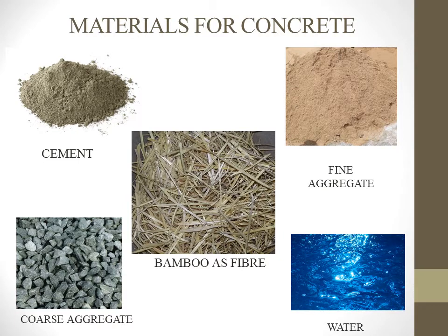These are the materials which we had used for concrete. Cement of 53 grade, JP branded. Fine aggregate from river sand, which is free of moisture, and then 20 mm coarse aggregate, and then water complying with the pH level, and then bamboo as fibers.